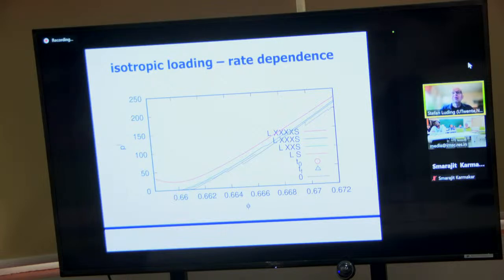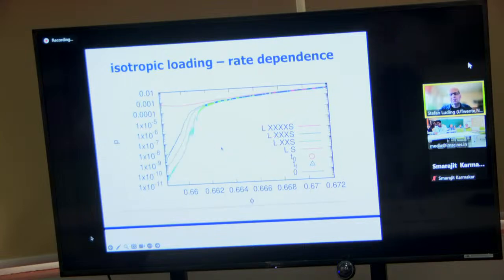And that's what I meant when I said you have to go really, really slow to see the phenomenology which I was talking about. Okay, and you see, fast rate, very smooth. The slower you go, the sharper these plastic events get. And then you can analyze them if you have them. With the magenta, with the fast simulation, you never can see the plastic events. Pressure in logarithmic scale as a function of density, and very low pressure means we have no elastic contribution, and here the elastic contribution starts to kick in, and at very high density there's no rate dependence anymore, because the rate effects are negligible as compared to the elastic effects.